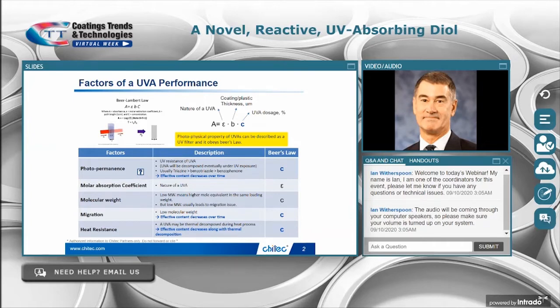Okay, for any discussion on light stabilization strategy, I like to start off with some background science. So here goes. The general strategy for obtaining good exterior durability in coatings is to use oxidation-resistant polymers and to use absorbers to absorb harmful UV light and then capture any free radicals that form using hindered amine light stabilizers. The UVA's effectiveness follows Beer's law, which is shown here on this slide. And the factors that impact Beer's law are which UVA is used, recognizing its coefficient of absorptivity, epsilon, and then the UVA loading in the formula and the thickness of the film. These all determine how much light gets absorbed.